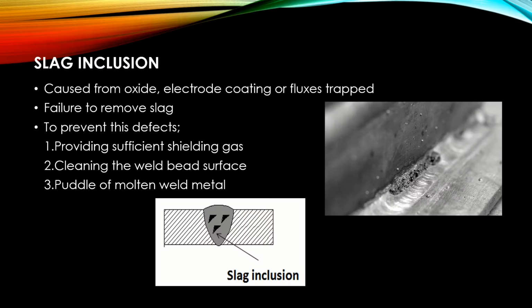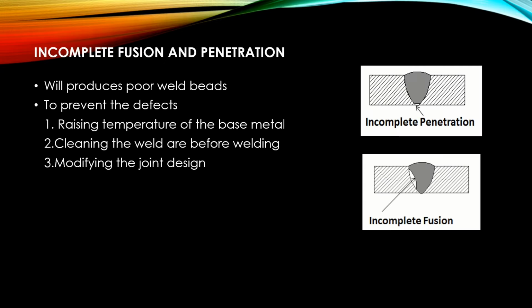And for the slag inclusion, it is caused by oxide, electrode coating or fluxes trapped and failure to remove slag. To prevent this defect, provide sufficient shielding gas, clean the weld bed surface, and the puddle of molten weld metal. And the third is incomplete fusion and penetration. It will produce poor weld beds, and to prevent the defect is by raising the temperature of the base metal, cleaning the weld area before welding, and modifying the joint design.